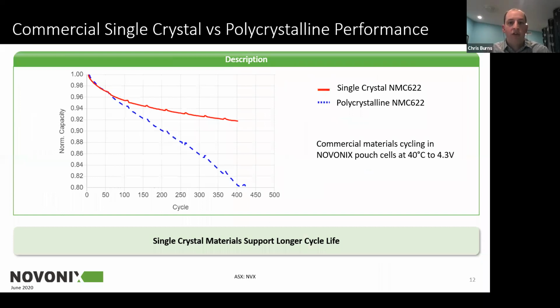And so when you look at some commercial materials for single crystal versus polycrystalline materials, we do all of this work internally with our pilot line in Halifax, where we build pouch and cylindrical cells and do extensive testing on our high precision systems: long-term cycling, power, rate capability, everything that you need to do to qualify high performance materials. You can see that when we build apples-to-apples cells and compare a single crystal NMC 622, so 60% nickel, to an analogous polycrystalline 622,